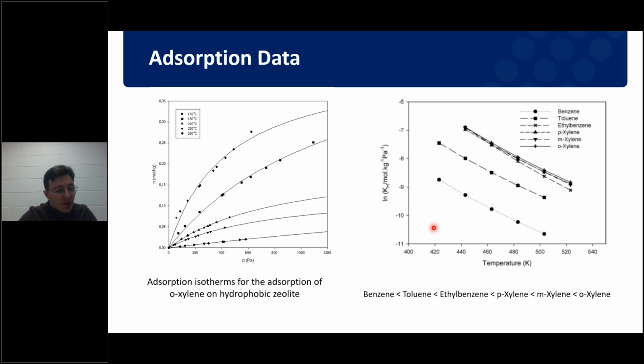On this next slide, we can see a couple of adsorption isotherms for o-xylene on this zeolite at a number of different temperatures. The equilibrium mole uptake is being measured here in moles per kilogram, seen on the vertical axis, and it's plotted against the partial pressure of o-xylene. And this has been done at a range of different temperatures.